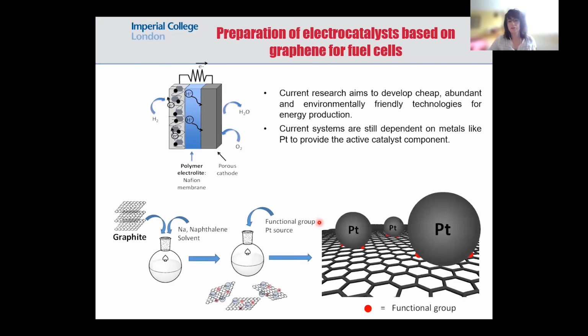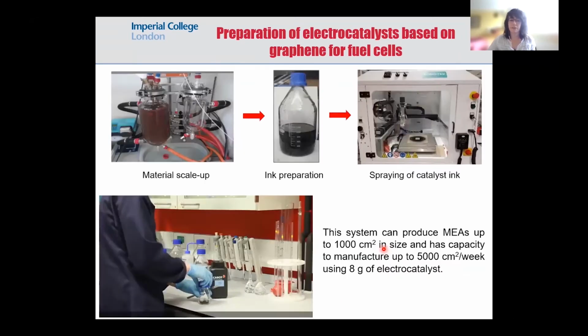So the idea is to use the same method that I described before, charging graphite to produce graphenes, and then we can use a platinum source that will reduce in situ to produce graphenes that contain these platinum nanoparticles, which are the catalysts carrying out the oxidant reaction in fuel cells. So we are able to scale up this process using reactors available at Cecilia's group. And in this way, we can prepare an ink that will be